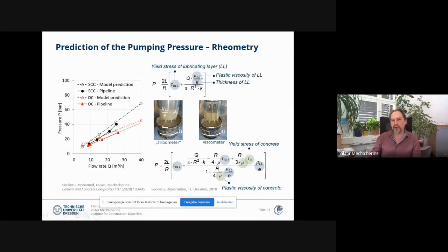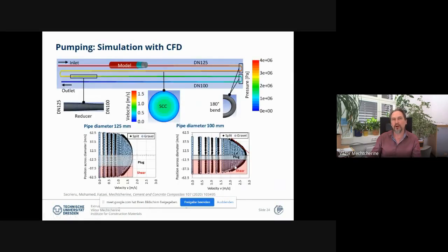We can also use these parameters derived experimentally for numerical simulation of the movement of concrete in the pipeline. In this case, we use the material law separately for lubricating layer and for the rest of the concrete in the pipeline. And by performing numerical simulation, we also can very nicely observe different phenomena like formation of the plug and region of the sheared concrete. And what we also can observe in this example in particular, how much the changes in the pipe diameter here from 125 millimeters to 100 millimeters change the shape of the velocity profile in concrete. And you see that the plug region, in this case, is much smaller than in the case of a little bit larger pipe diameter.